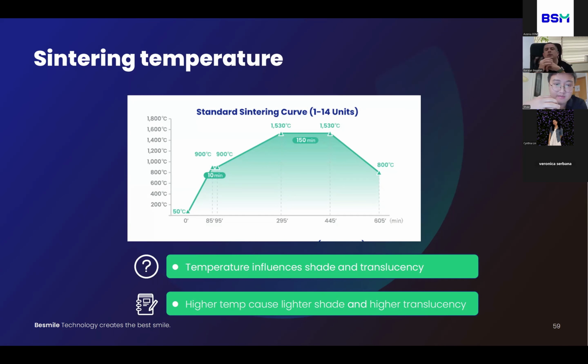From our test, if you change the temperature by 30 degrees, decreasing or increasing it, there's a half degree of shade change after you sinter the crown. For example, if you increase the temperature by 30 degrees, after sintering, the A3 crown might change to an A2.5 crown, so the shade will be between A2 and A3. Okay, so in this way, we can adjust the shade a little bit as we want.